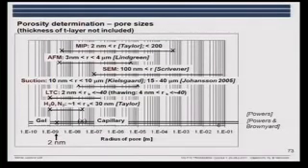This is a graph showing the applicability of the various methods, in which range you can use them. I haven't included the NMR, but that would be in the entire range. What you see is that if you're using low temperature calorimetry, which you could use on a virgin sample, which could be quite useful, you cannot describe the larger pores well. In the larger range, it will be from about 40 nanometers or something like that, and then upwards. And then you will have a signal for all the bulk water freezing in your sample.